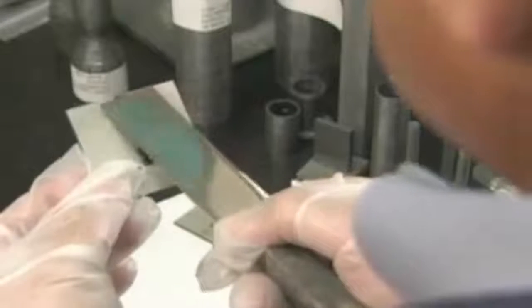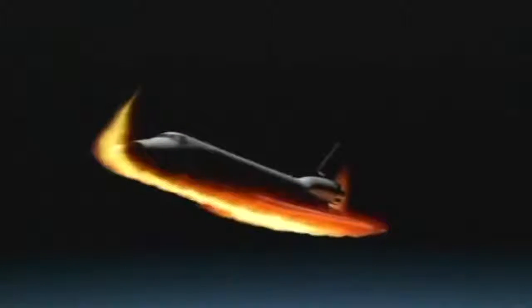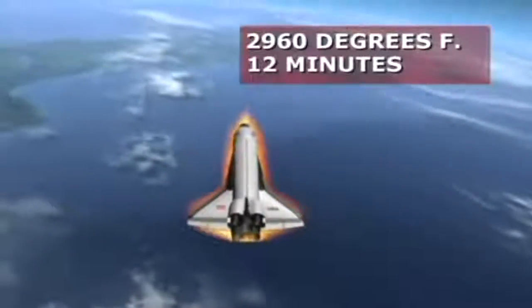Grabber would be used to fill cracks, but it would have to withstand some pretty tough conditions. During re-entry into Earth's atmosphere, temperatures on the leading edge of the shuttle reached 2,960 degrees Fahrenheit for about 12 minutes. Grabber, which converts from an adhesive to a high-temperature ceramic during re-entry, underwent harsh tests at NASA. Carbon-carbon composites repaired with Grabber were submitted to 1,650 degrees centigrade temperatures for 12 minutes. After almost 10 minutes into the test, the reinforced carbon-carbon disc material, which is a substrate, started failing, burning near the holders. But there was nothing wrong with the crack repair material. All the material is still intact.